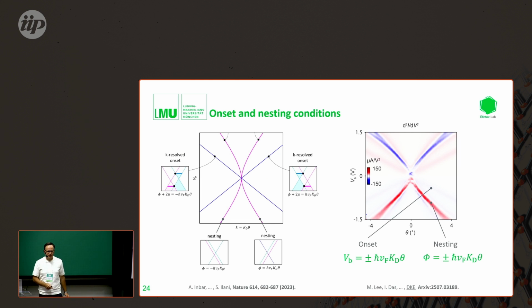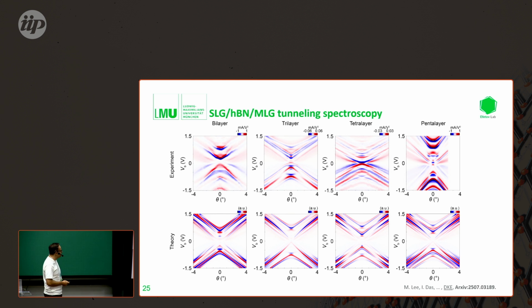So I probably still have 5 minutes. Okay, all right. With those nesting and onset conditions, we can understand these features that we observe. And of course, this is not just limited to single layer graphene, because we took many different measurements on single layer to multi-layer graphene tunneling. This is, for example, tunneling into bilayer graphene, into trilayer, tetralayer, pentalayer. All of those conditions that you see here are some sort of nesting or onset conditions that are sensitive to the band structure you tunnel into.